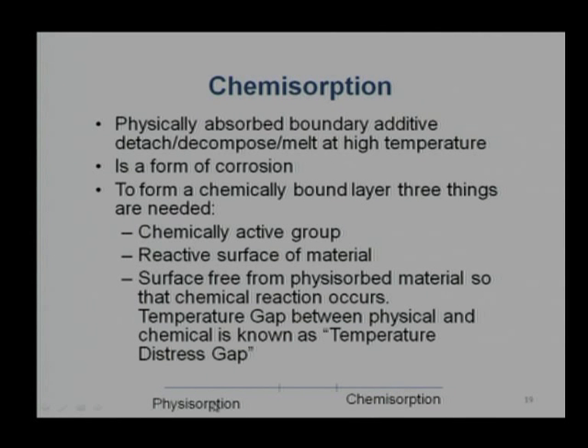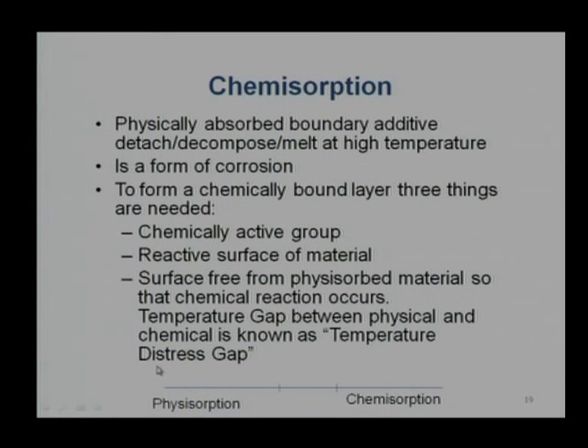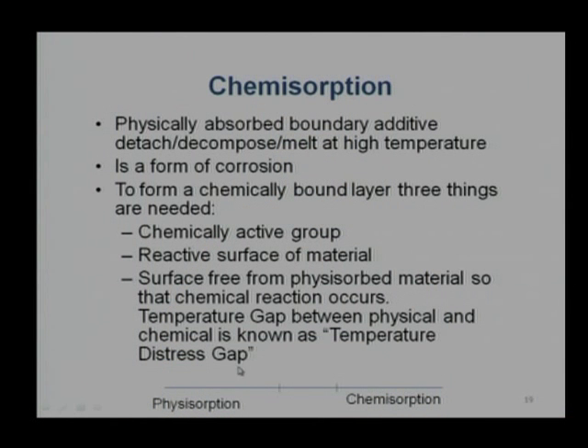The reason being, if there is physical adsorption, if there is a lubricant layer already there, then chemical adsorption will not happen unless the surface is completely clean. If there is something already on the surface, it will not be reactive towards the chemically active group. So, there needs to be some gap, and that gap is known as the temperature distress gap. We should never operate the equipment in that gap, either on the lower side or the higher side. So, we need to design so that this temperature distress gap is minimum, or we should not use one metal or one additive. We may use a composition with an active group for physical adsorption at low temperature and another group at high temperature. So, two different groups are used. In that case, quite possibly there will not be a temperature distress gap. It can be without that gap.